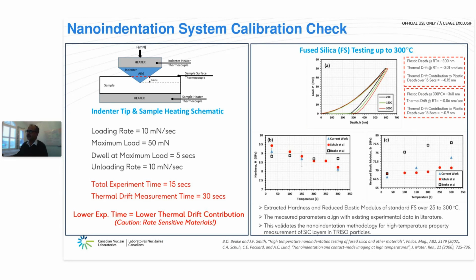Before we start testing, we do the system calibration check on a reference material, which is fused silica, and we tested the silicon carbide coatings in the initial run only up to 300 degrees C. Although the pursuit is to go up to the reactor relevant temperature of 1000 to 1200 degrees C, given the challenges involved with extremely high temperature indentation, we have started to generate this data set for these silicon carbide coatings in TRISO for moderately high temperatures up to 300 degrees C.